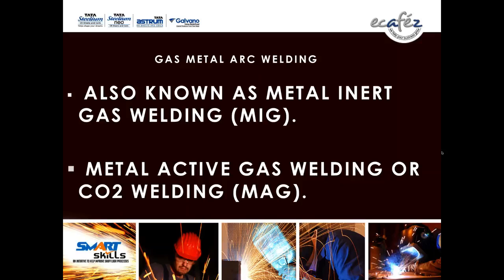Yes, we are going through MIG welding. SS welding using MIG welding best practices. If you do the welding process in your workshop, you can go for MIG. For the MIG process, select the proper shielding gas for your application. The shielding gas for stainless steel should be 99% argon, 1% O2 or 98% argon, 2% O2, for a stainless steel butt joint by MIG process.